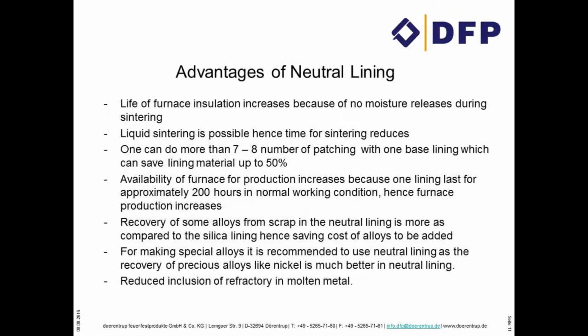So a major advantage of the neutral lining is that the insulation of the furnace increases because there is no moisture in the lining, and moisture release is not there during the sintering heat. Then liquid sintering is possible, so you can reduce the sintering time of your furnace.